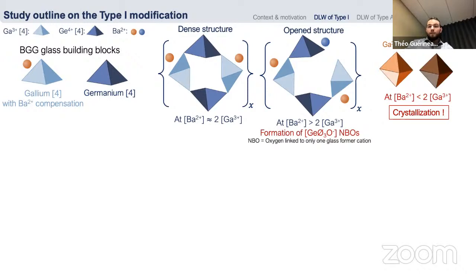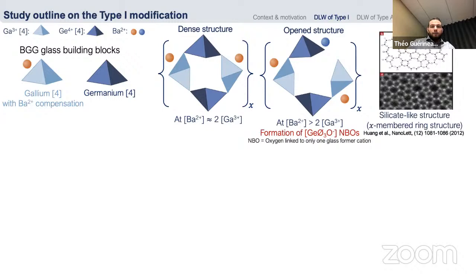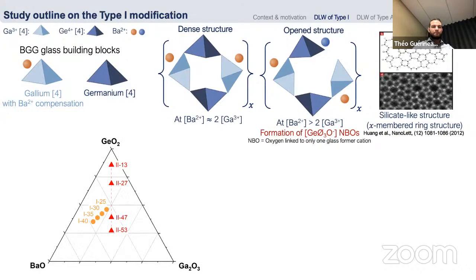And when we decrease the concentration of barium, there is the formation of gallium in a 5-fold or 6-fold site. But we must avoid this kind of case because we reach the devitrification of our glasses very easily. For people that are more familiar with silicate glasses, the BGG glass structure is very close to what we can find in this type of glasses.